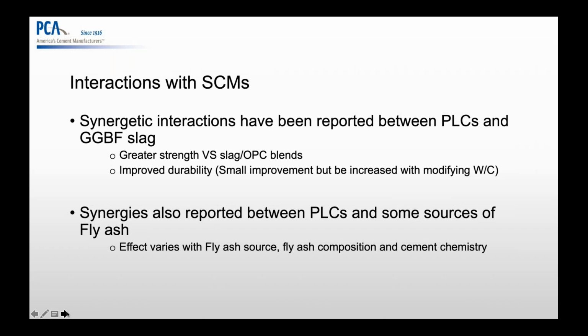The interaction with supplementary cementitious materials, like what? Like slag, class C fly ash, class F fly ash, silica fume, even in the future, ground glass or some other ones. Portland limestone cement has an affinity for SCMs, and the reason why is that there are calcium carboaluminates that provide a modified hydration during the strength formation, and that provides even added durability when the water cement ratio is optimized in your mix designs, and it also provides increased strength at longer periods.